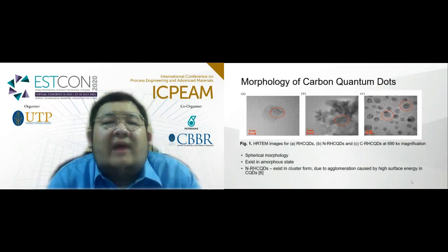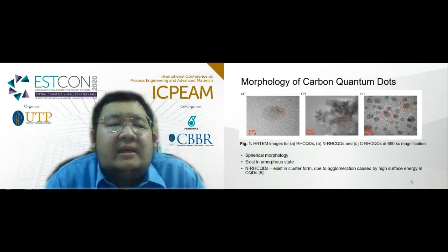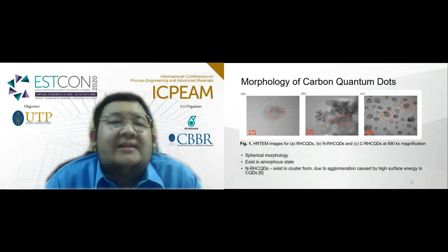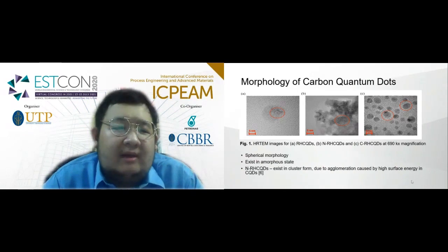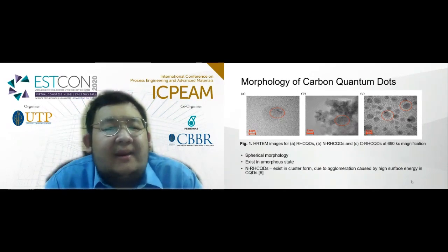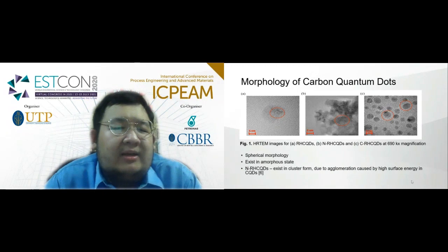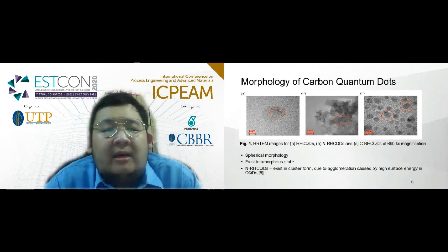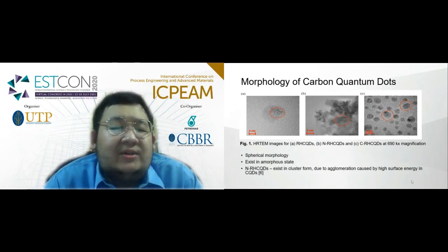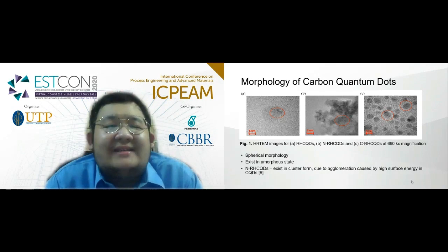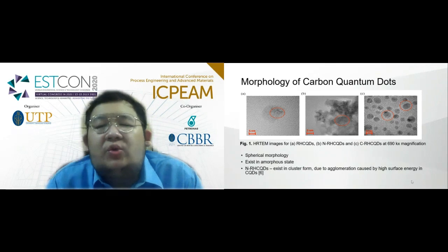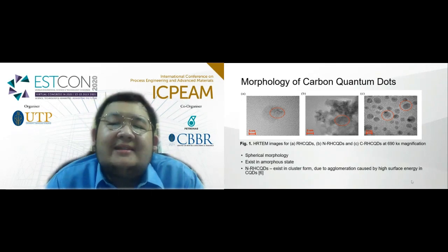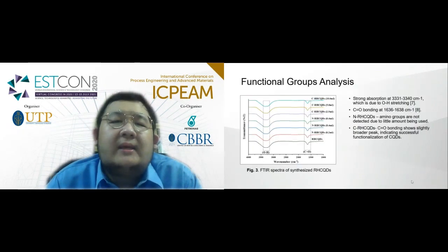The morphology of carbon quantum dots is tested using HRTEM. This indicates the successful formation of carbon quantum dots, which exhibit spherical morphology and exist in an amorphous state. In the case of nitrogen-doped NCQD, it exists in cluster form. This is due to the agglomeration caused by high surface energy in the CQD.